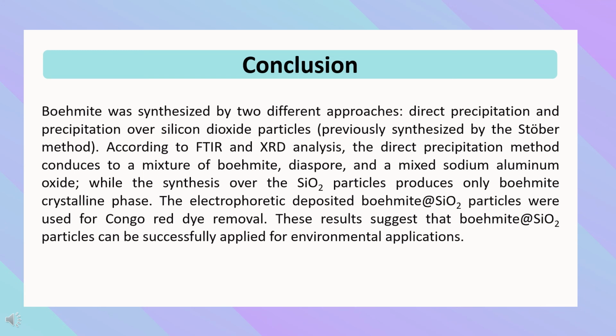In conclusion, boehmite was synthesized by two different approaches, direct precipitation and precipitation over silicon dioxide particles, previously synthesized by the Stöber method. According to the FTIR and the XRD analysis, the direct precipitation method leads to a mix of boehmite, diaspore, and a mixed sodium aluminum oxide, while the synthesis over the silicon oxide particles leads only to a boehmite crystalline phase. The electrophoretic deposition of boehmite on silicon oxide particles was used for Congo red dye removal. This result suggests that boehmite particles can be successfully applied for environmental applications.